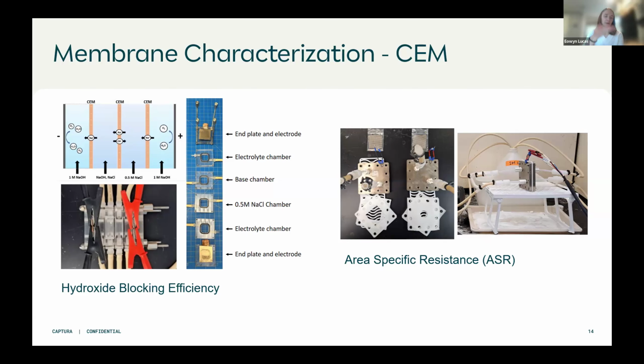And so the first thing that we do is we measure what we call hydroxide blocking efficiency. So in this case, we've developed similar to the cells you just saw, but we've rearranged them slightly, and we flow base on one side and salt on the other, because this is the condition that the membrane will see in that full stack that I shared earlier. And then we measure the amount of hydroxide that leaks across that CEM into the salt channel. And this is a key characteristic when it comes to these full stacks.